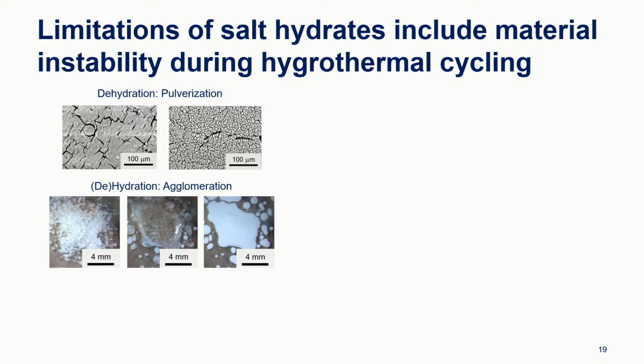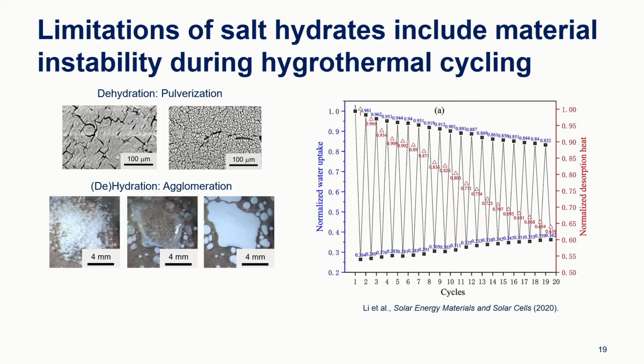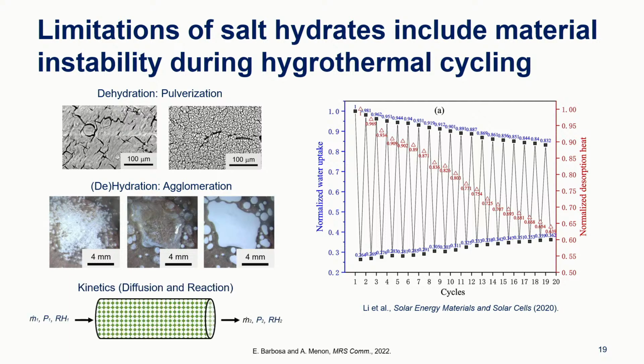which is no longer going to allow you to transport water vapor effectively. And so these are some of the major challenges, and that has affected the energy density, or the reaction enthalpy, over a few cycles. So it starts up over here, but as we cycle the material, even just 20 times, that energy density drops to 60%. That is because of these instabilities or irreversibilities in the chemical reaction itself. And as a result, your reaction is also going to become a lot slower. So the kinetics are going to be slower because you have all of these non-ideal states.